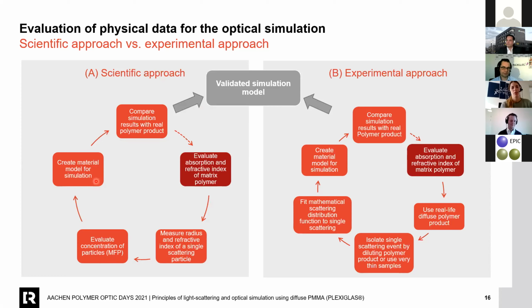If you have all this information, you can create a material model for the simulation and compare this with the measured results of your polymer product. If the results are good, you have a validated simulation model. And if not, you have to start from the beginning and do all the steps again. On the other side, you have the experimental approach. You also start with the evaluation of your matrix polymer, but then you use a real-life diffuse polymer product. If you have this product, you need the information of your single scattering. So you have to isolate the single scattering event by a dilution series, or you use very thin samples.